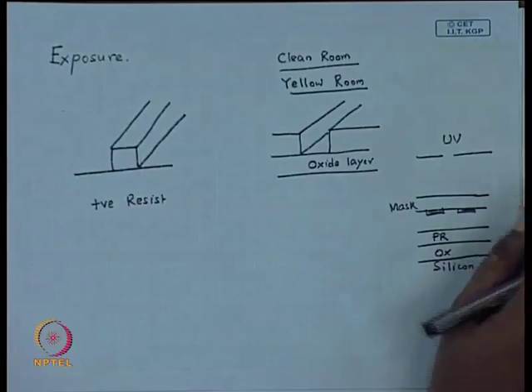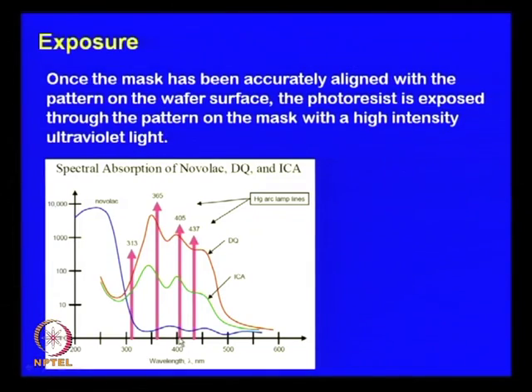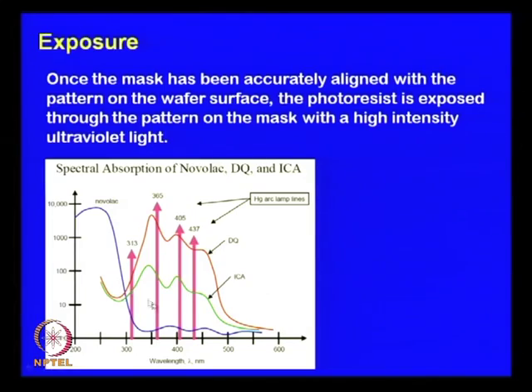And the reason is, if you think of the concept of VIBGYOR, the constituent lights which make white light, violet is closest to the 400 nanometer wavelength, and yellow and red are closest to 700 nanometer on the other side of the spectrum. Here, if you look at the absorption curve, these photoresists show a maximum absorption peak at around 350, which is sub visible, or in the UV range. However, between 400 and 500 there is still some bit of absorption.